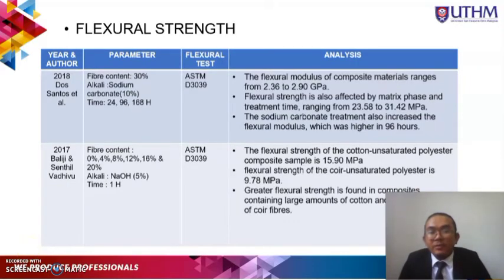Alright, for the flexural strength, Dos Santos found that the flexural modulus of composite material ranges from 2.36 to 2.90 GPa. Flexural strength is also affected by matrix phase and the treatment time, ranging from 23.58 to 31.42 MPa. The sodium carbonate treatment also increased the flexural modulus, which is higher at 96 hours.